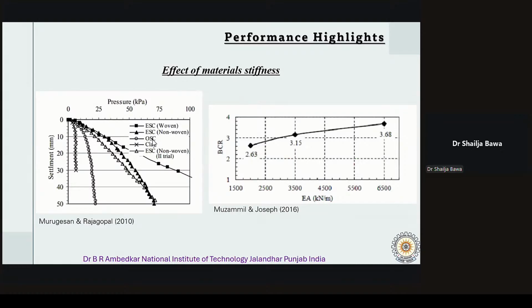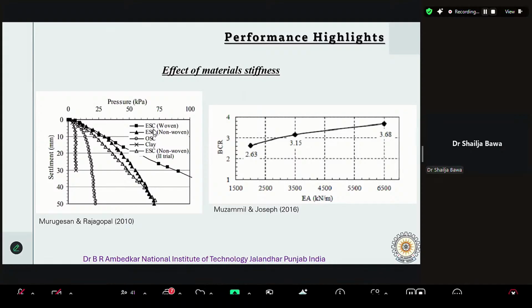So again, you can see how the stiffness of the encasing material informs performance. Here you can see the woven types of geotextiles perform the best, showing the least settlement under increasing pressure. But ESC with non-woven geotextile, the triangles, though perform slightly less effectively, still do much better than unreinforced clay and ordinary stone columns. And the clay layer without any column shows the highest settlement, indicating poor performance. The second trial of ESC with non-woven geotextile confirms the consistency in its yield. So this confirms that woven materials, which are stiffer, provide better lateral confinement,